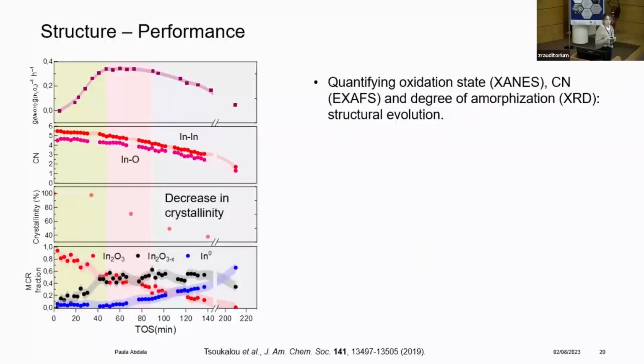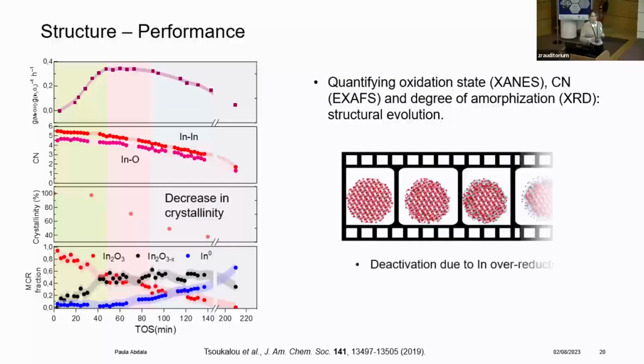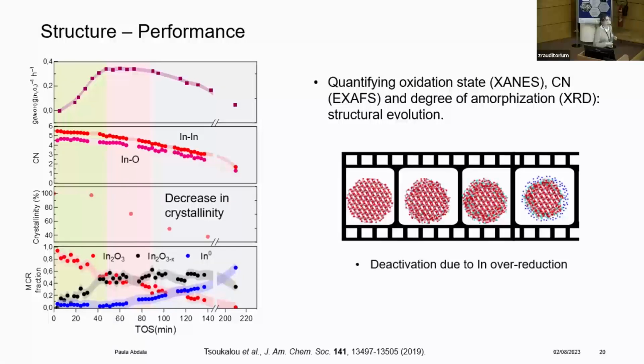So we can put all this information together and correlate structural parameters with the simultaneously acquired methanol GC data. What we learn from this is that the most active state of the catalyst corresponds to an oxidation state of indium that is between indium +3 and +2. So it's partially reduced, meaning there is a formation of oxygen vacancies to compensate the charge. Yet, under certain conditions, it can also over-reduce, leading to the formation of metallic indium. And metallic indium under this reaction is molten, which also explains the decrease in crystallinity. What we propose is that this over-reduction leads to the deactivation of the catalyst with time on stream.